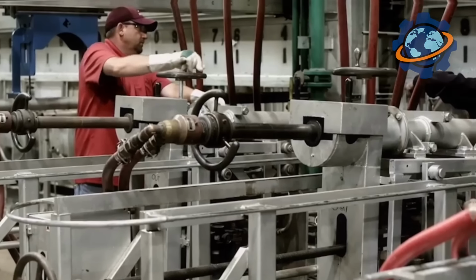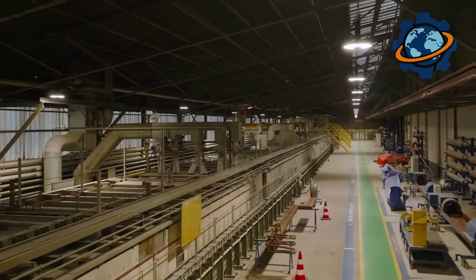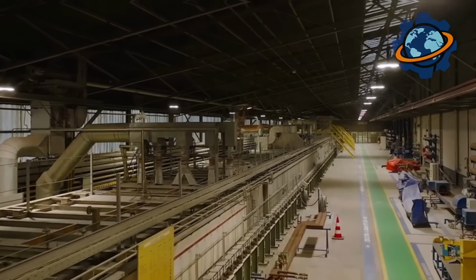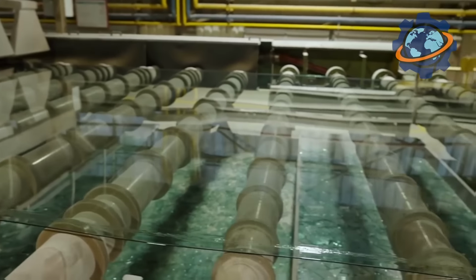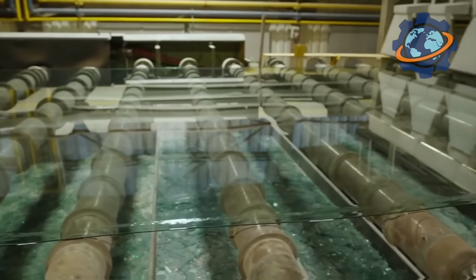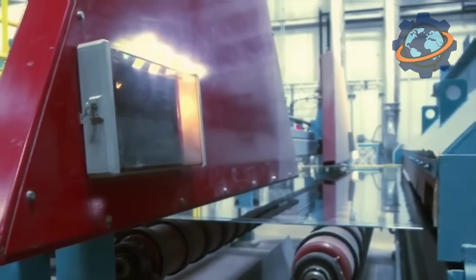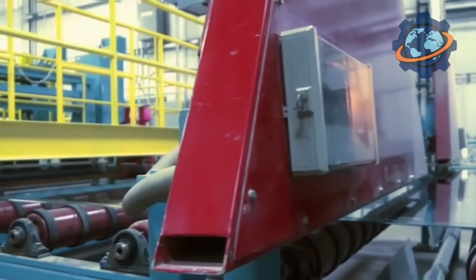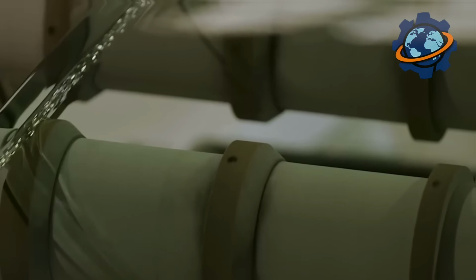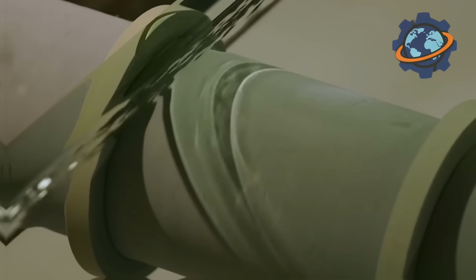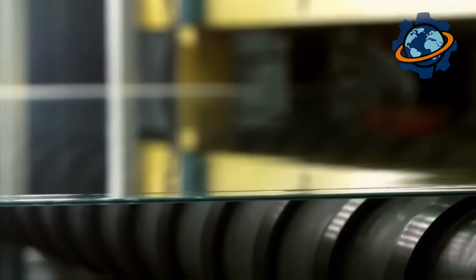But raw glass is dangerous. Sharp edges could slice arteries. Grinding wheels smooth every edge, creating a slight bevel preventing cuts. Then washing. Automotive glass undergoes a cleaning process NASA would envy. Deionized water rinses away particles. Even microscopic contamination shows up later. One speck of dust between windshield layers creates a bubble visible to the driver, requiring part rejection. Cleanliness isn't preference, it's requirement.